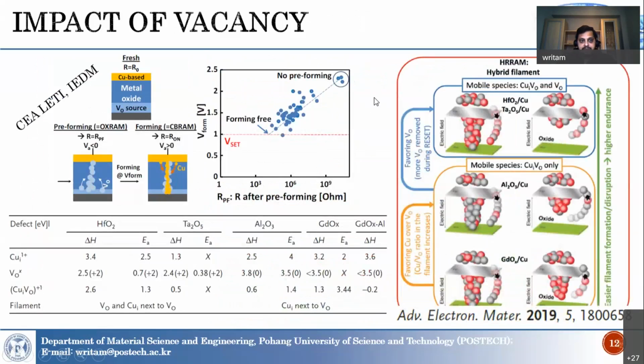Previously it was also reported from Leti, and also recently from one paper in Advanced Electronic Materials, that if oxygen vacancies are present in standard RRAM devices like silver-based or copper-based ECM type devices, there is a decrease of the operating voltage. At some point, by controlling these vacancies, it's possible to have even a forming-free structure. So the presence of vacancies can dominate the switching possibility of any structure.